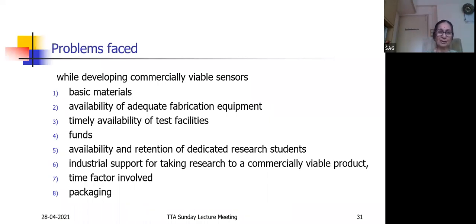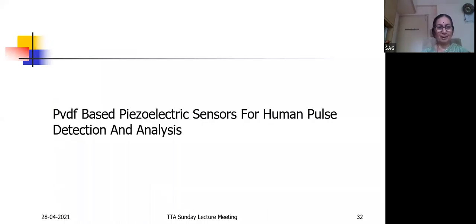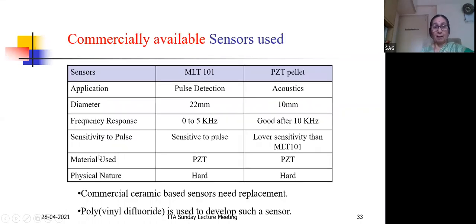I'll be talking on these problems first when I'm explaining to you the sensor which is developed in my laboratory. This PVDF-based piezoelectric sensor for human pulse detection, which we developed. We were having commercially available sensors for pulse detection. The diameter was 22 millimeter. Frequency response was 0 to 5 kilohertz. It was sensitive to the pulse.